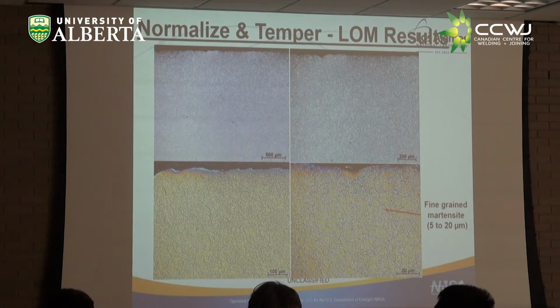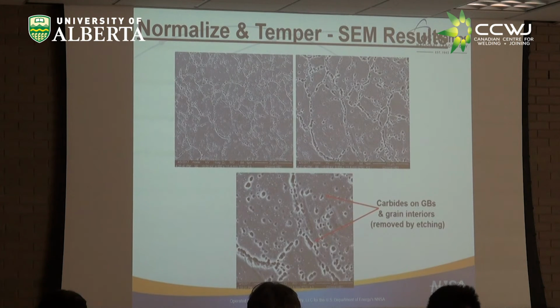If you then take the material and go through the normal heat treatment you would go through for a raw material, including this normalizing, which again is reaustenitizing, dissolving the carbide, and then rapidly cooling, and then tempering, you get exactly what you're supposed to get, and this is characteristic of the microstructure you see. This is not high enough mag, but the microstructure you see here is characteristic of martensite, which is what we expected in the as deposited microstructure. It's fine grained. It's actually better, smaller grained than the wrought material. And in fact, I think I have some TEM here, but this is actually probably better than the wrought material from an irradiation tolerance point of view.